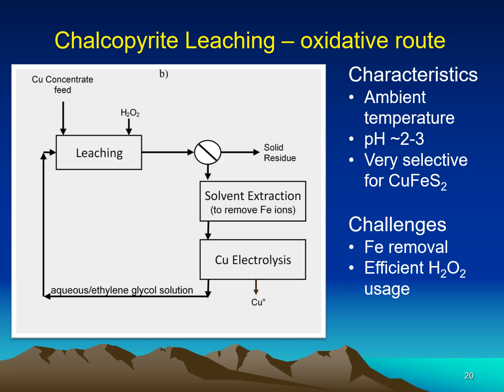Like a very conventional diagram. However, in this case, we would like to reduce the hydrogen peroxide consumption. And this is done by including in the aqueous solution ethylene glycol, or other polar organic solvents have been used. And in this case, we can reduce the amount of hydrogen peroxide consumption.